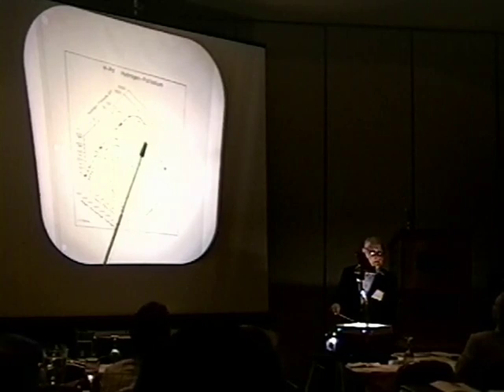So what happens is first the temperature goes up fast, the discharge begins slowly. It goes up into this range. There's a 500 degree C line. Finally, the discharge has accelerated and the gas is gone and there's no reason for any excess heat. And this is judging by the heat production equation you saw about 13 and a half minutes ago.